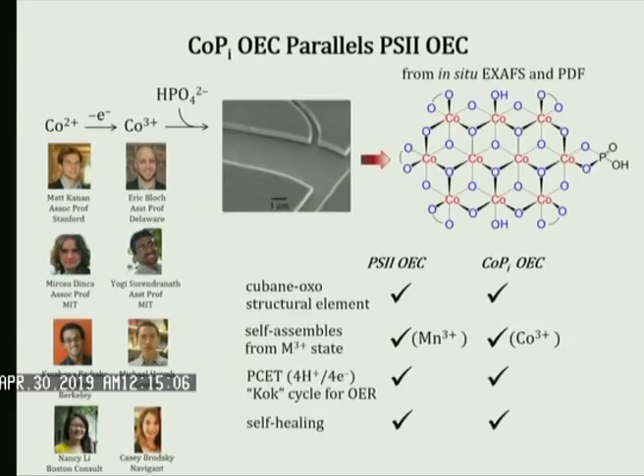And it took many years. We figured out what the thin film was made up of. It was made up of these clusters of cobalt and oxygen, so that's number one. And it had a lot of interesting properties, but the one especially important to the GILS program is this catalyst could do this special thing called self-healing. And so what it can do is fix itself in real time, always fix itself.